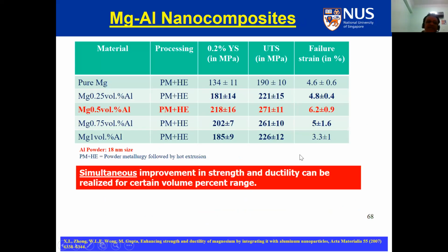So we started with microwave. We put a very small amount of nano size aluminum particles. And look at this highlighted red font row here, which shows that by putting the nanoparticles in a very small amount, 0.5 volume percent, you can get a simultaneous improvement of the yield strength from 134 to 218 megapascal, ultimate tensile strength from 190 to 271 megapascal, and you can make the ductility 1.5 times, from 4.6 to about 6.2. And this is amazing because now you're improving both strength and ductility of a material just by putting in 0.5% of aluminum.